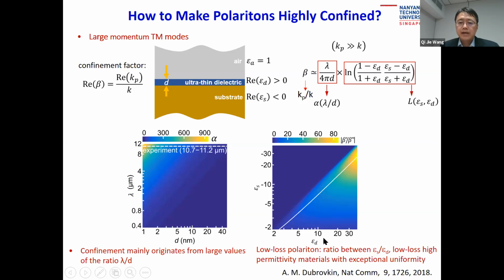So in a way, it shows that we need to optimize the ratio between the two layers, and we need to have the dielectric and the substrate layer has high permittivity as high as possible, and also low loss in the mid-infrared region, and with exceptional uniformity with a super flat surface. So that's the task. So we identify in this case, then we propose to use silicon carbide as a substrate, provide the Phonon-Polaritons, and then you can use a 2D material in this case, because 2D material really guarantee high uniformity in a large area.